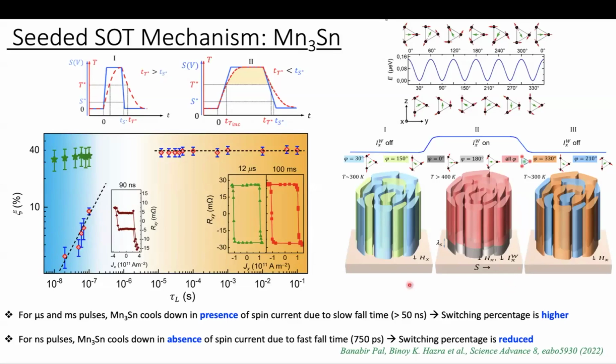We have also performed another experiment with the nanosecond pulse. When we apply an additional current, an additional DC bias, we observe the switching percentage increases. So from this experiment also we can tell heat plays a role in this switching.